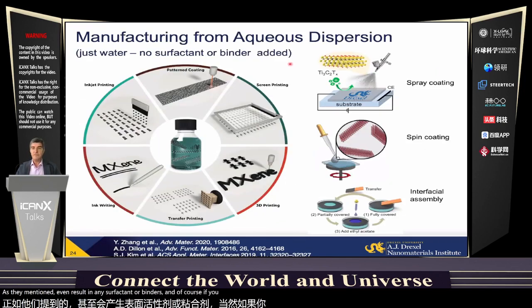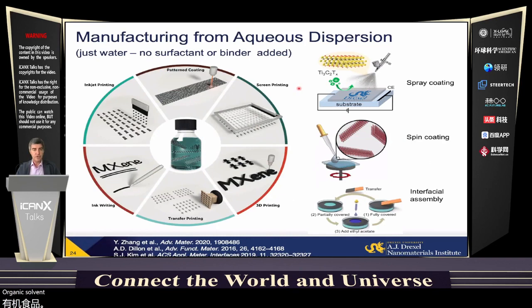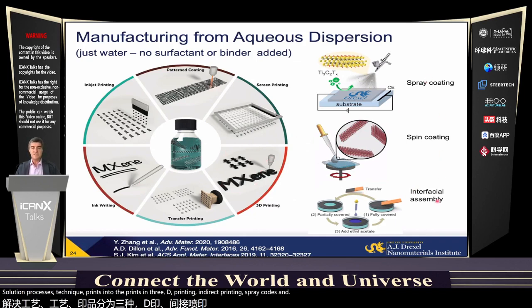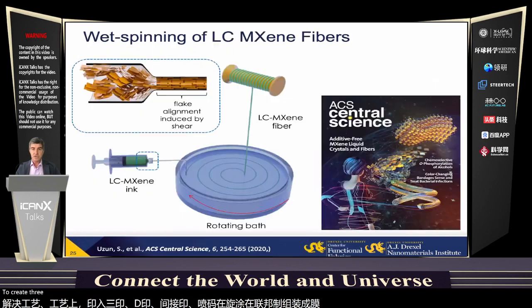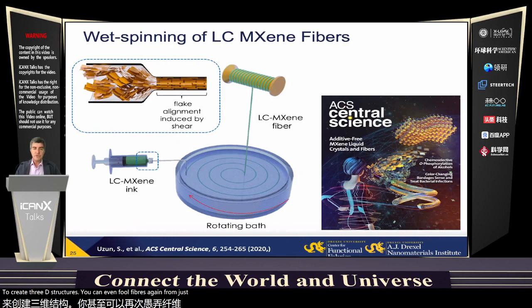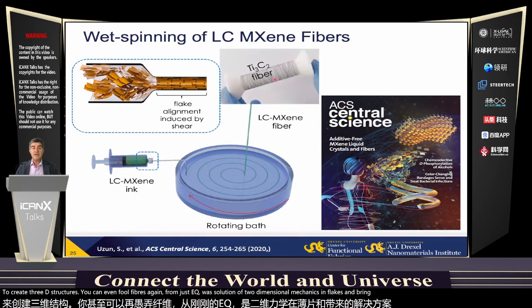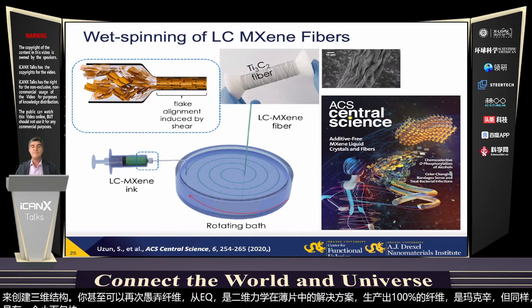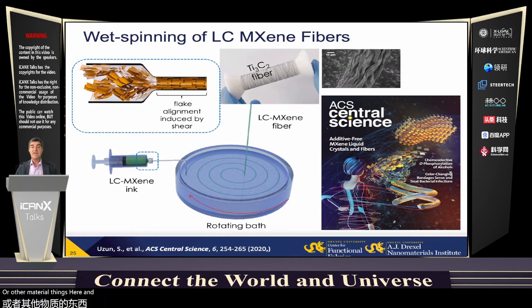And of course, if you have colloidal solution of 2D particles in water, or you can transfer it to organic solvent, polar organic solvents, you can use all the variety of known solution processing techniques: printing, 2D printing, 3D printing, inkjet printing, spray coating, spin coating, interfacial assembly to create films, to create 3D structures. You can even pull fibers, again, from just aqueous solution of two-dimensional MXene flakes and produce fiber, which will be 100% MXene, but again, you can mix it with graphene, you can mix it with carbon nanotubes or other things here, and it will give you conductivity.